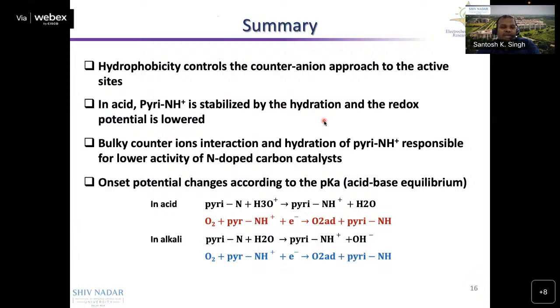Hydrophobicity of this catalyst controls the counter anion approach to the active sites, which keeps the active sites fresh for further catalytic reactions, and also the pyri-NH+, which is stabilized by the hydration of water molecules. That could be prevented by the introduction of hydrophobicity, and the bulky counter anions are one of the biggest reasons why this pyridinic nitrogen is showing very low activity. And the onset potential changes according to the pK of the acid and base like solution.